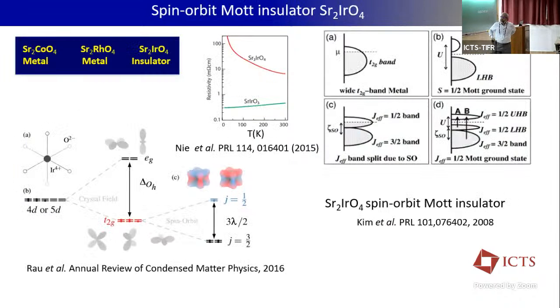So here let me start with one candidate material, that is Sr2IrO4. If you look at its 3d counterpart, this is Sr2CoO4. The 4d counterpart is Sr2RhO4, and the 5d counterpart is Sr2IrO4. As I mentioned, as you go from 3d to 5d, the orbital gets extended. Naively, one should expect that if Sr2CoO4 is a metal, Sr2IrO4 will have more metallic character. But what is seen is that Sr2IrO4 is an insulator. This is the data, resistivity versus temperature. You see, this is Sr2IrO4, and it shows a strong insulating character.